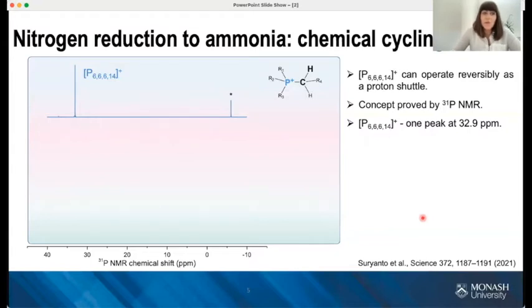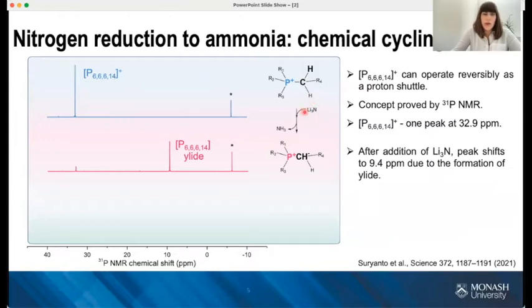But to confirm the capacity of that phosphonium cation to operate as a reversible proton shuttle, we performed a series of chemical experiments that simulate the transition between this phosphonium cation and the ylide. And we monitored this process using phosphorus NMR and mass spec. So as you can see here in the figure, the phosphonium cation produces one peak on the phosphorus NMR around 33 ppm, right? And after the addition of lithium nitride, this peak is shifted to 9.4 ppm, and this is due to the formation of the ylide. This value is in agreement with the available literature, so that confirms that this ylide is